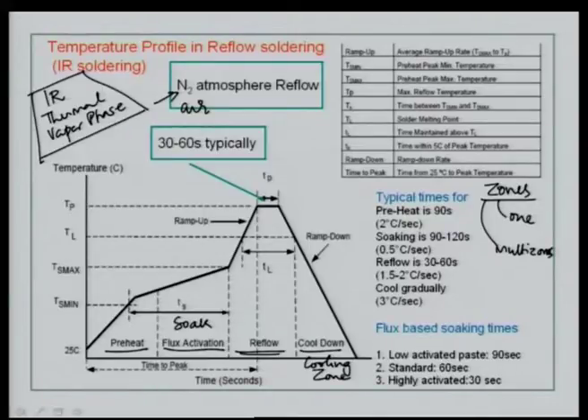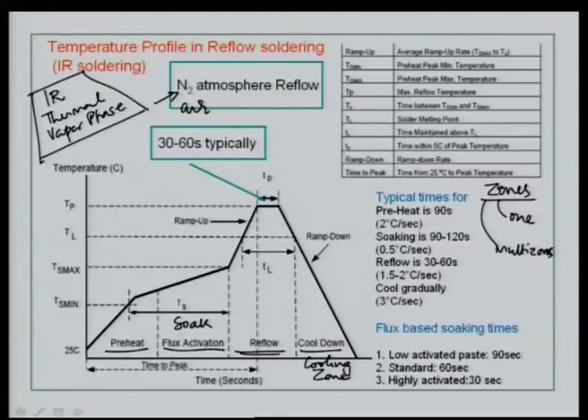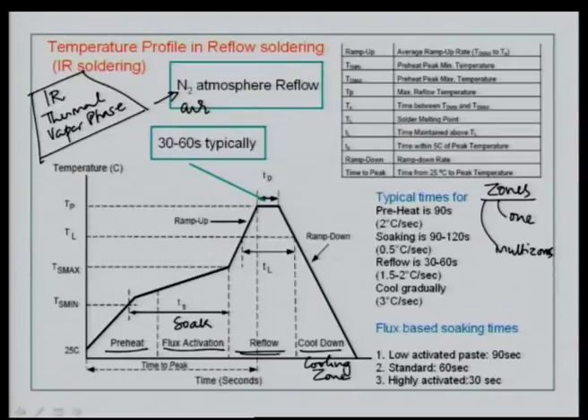Cooling should be a very slow process — you should not immediately remove the board after peak reflow because that would cause thermal shock. Therefore, the cooling process also has to be well defined. We start with room temperature, let's say 25°C, then slowly move to a predefined temperature — the preheat peak. This could typically be from 25°C to about 150°C depending upon the Tg of the board. You want to activate the interconnects, the copper, and also remove moisture from components.